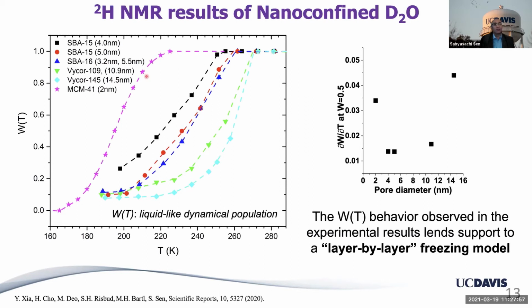as it should because of the freezing point depression. But also, one thing to note is that the drop is the steepest, from purely liquid fraction to almost purely solid fraction. The drop is steepest for the smallest size pore and for the largest size pore. In between, they sort of go gently down from fully liquid-like to fully solid-like spectrum.